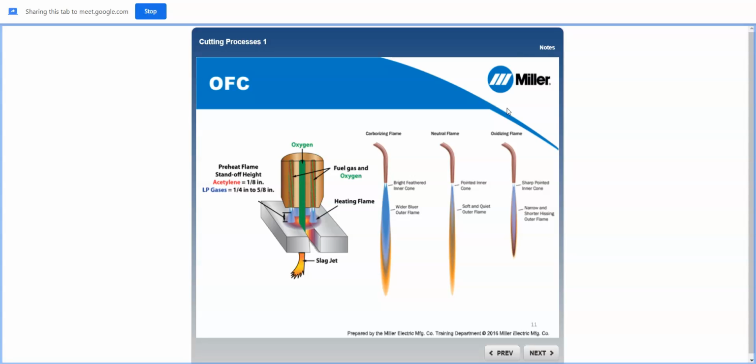Adjusting the oxy-fuel flame is a critical variable, where with a plasma arc, merely the amperage could be adjusted to optimize the cut quality and consumable wear. The neutral flame of an oxy-fuel flame is about 5,600 degrees Fahrenheit. This neutral flame is used to preheat the base metal, allowing a pure stream of oxygen to rapidly oxidize the carbon steel below.